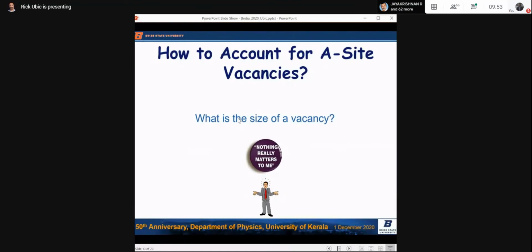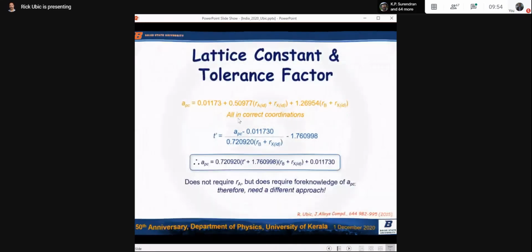So the point is you can use the Shannon tables to find the sizes of almost everything on the periodic table, but what doesn't appear on the periodic table is vacancies. So how do you calculate the size of a vacancy? It's not 0. It's almost never 0. So what's the size of a vacancy? That was the problem we encountered next.